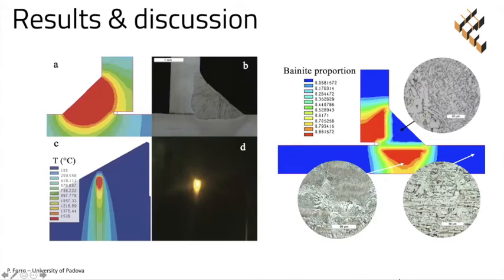The figure on the left shows some thermal results. In red, you can see the fusion zone shape and dimension that was found in sufficiently good agreement with that obtained in the experiments. In the figure on the right side, the numerical result of bainite proportion after welding is shown. In blue are zones characterized by a fully ferritic microstructure. The fusion zone microstructure consists of acicular and Widmanstatten ferrite with islands of allotriomorphic ferrite, in agreement with the microstructure observed in low-carbon steel welded joints. The heat-affected zone, on the other hand, was mainly composed of bainite as predicted by the model.